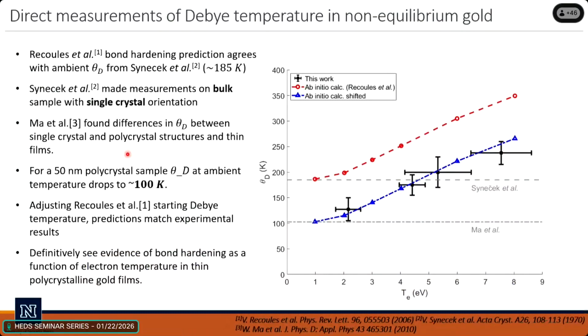Now, it actually doesn't matter because the bond hardening paper is sort of like about here. So the Debye temperature is actually not that different to single crystal Debye temperature, right? But just seeing where we end up on here. So it changes the superheating result from maybe 14 times to like 12 times the melt temperature. So it doesn't make a difference. But I will say that I was worried when I did this. I was like, oh my gosh, is the Nature paper completely wrong? But it's okay. Thanks.